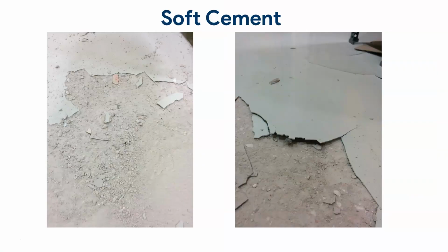Moving on, let's look at soft cement. I mentioned at the start that you can apply epoxy on concrete. With soft cement, it's a bit trickier, and that's why I have posted these two pictures here, and I've done an entire video on this subject. This is what I mean by soft cement. When the cement underneath has all these little pieces coming out, and it's very dusty, this is a classic example where the epoxy was applied on top, and it just failed.